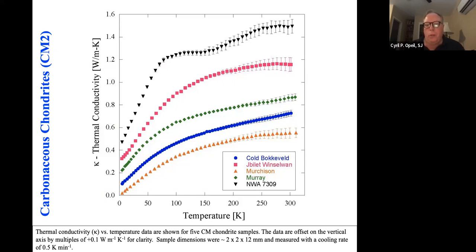And so the thermal conductivity will not have a very large peak, though for the NWA 7309, that's actually having the largest, it's trying to rise to a peak, but it probably has the most order as opposed to the other ones. And so we can see as it decreases from 300 Kelvin down to zero, these are kind of monotonic. And obviously these are very low thermal conductivities, well below 2 watts per meter Kelvin.